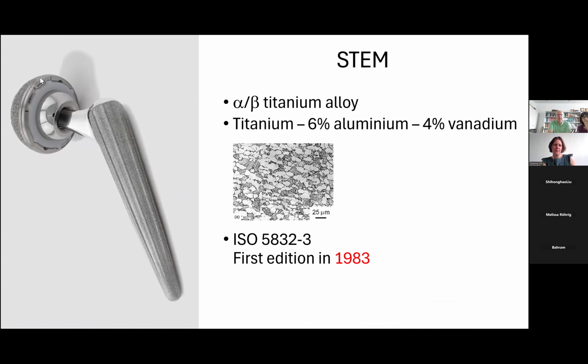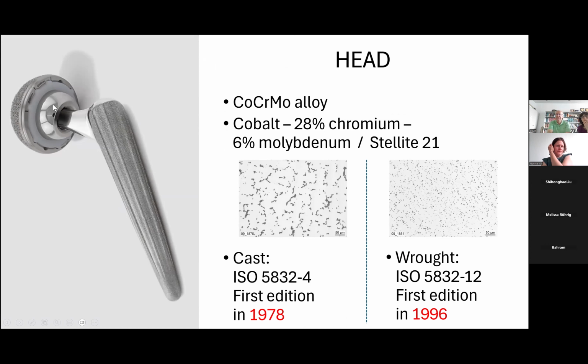If you have a look now at the ball head, the ball head is mainly made of a cobalt chrome alloy. It is a kind of Stellite 21. And you have two qualities. You have the cast, where you see here the carbides, the dendritic carbides. And here you have the wrought version. The composition is exactly the same, but you can see also here that the first edition was quite old, 1978 for the cast and 96 for the wrought alloy. It means they are fixed alloys, and the whole industry is working with this type of alloys.